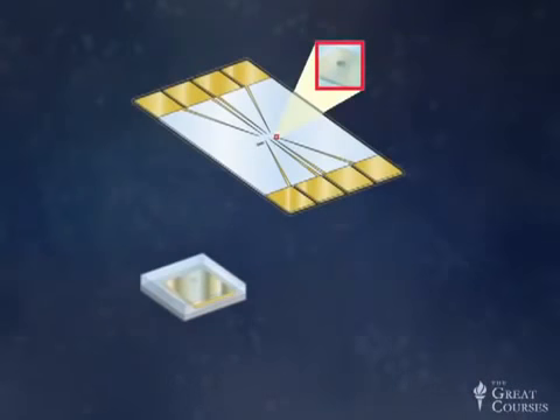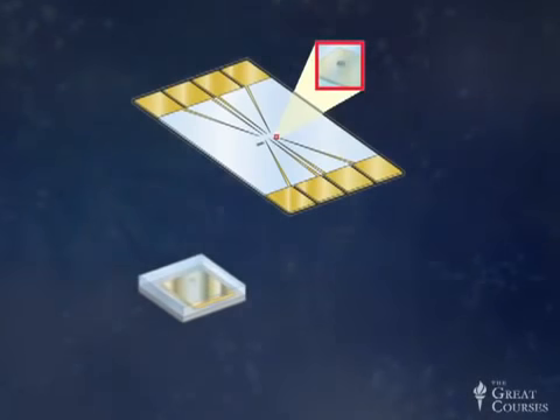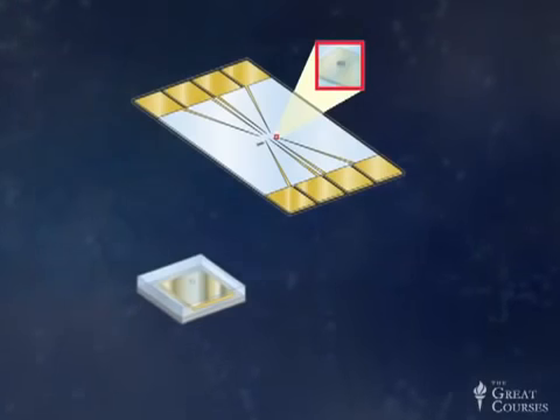Now, the printing of this chip on a silicon wafer is not what gives us our nanoscale features. Instead, it's what we actually do once we bring the chip in the lab. So the chips get fabricated at a semiconductor fabrication facility, and then they come back to us and we post-process them. So if you look at the surface of our chip, you wouldn't be able to see this by eye. But it turns out that there are tiny holes in the surface of the chip, and they were put there purposely to provide a place for us to introduce nanomaterials.